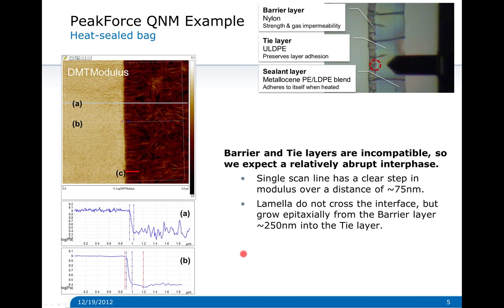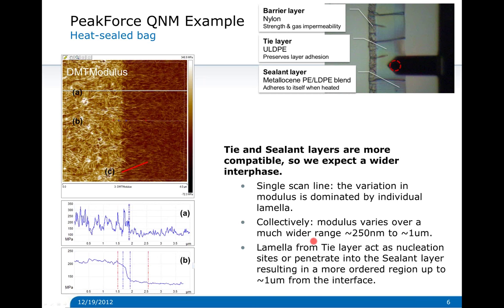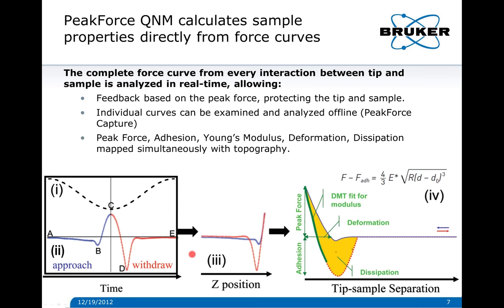You can look quantitatively at the modulus in each region and study how compatible the different materials are, and examine the length scale of the interface between the two materials. The modulus is changing over a range of around 75 nanometers, and this ordered area of lamellae results in a secondary drop extending up to 250 nanometers into the tie layer. At the other boundary, where there are more compatible components, the lamellae grow from one domain into another, causing the variation in modulus to be much more gradual.